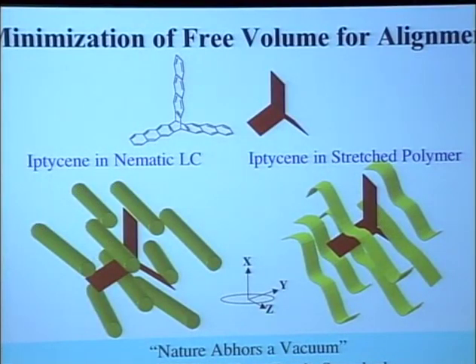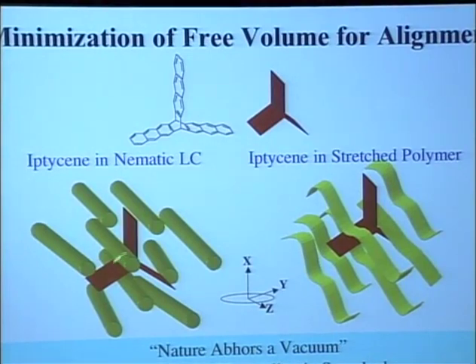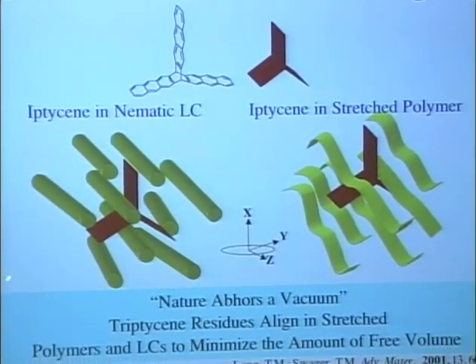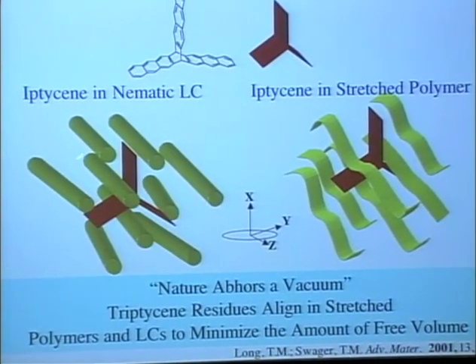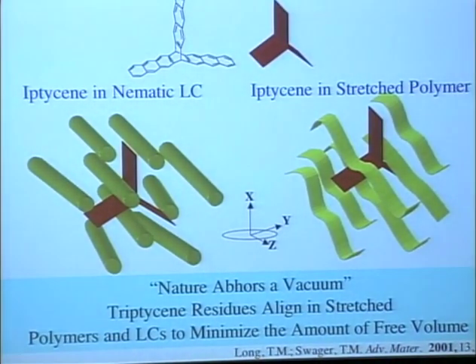But using free volume is more important in the alignment than the actual aspect ratio of the materials. You think about it: if you throw another stick in here, it will align with the liquid crystal. You throw a stick where you pose the free volume directly, diametrically opposed to that axis, and the free volume will win. It also works in polymers, where the polymer chains tend to thread through these free volumes. So these materials are fundamentally driven by thermodynamics to organize this way. And I'll show you how we can use that in a variety of different ways.